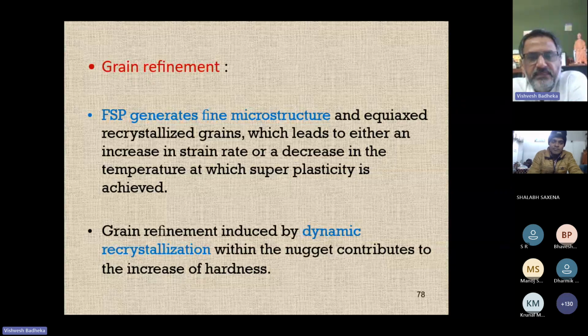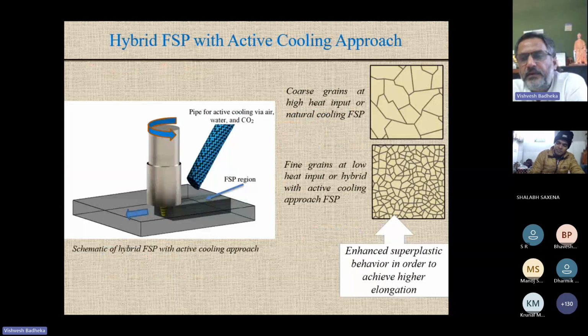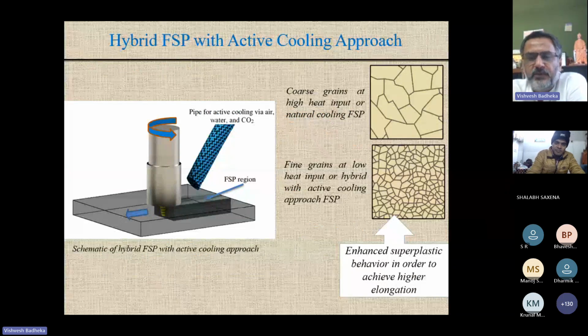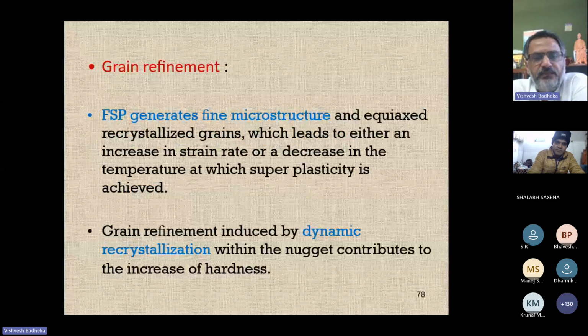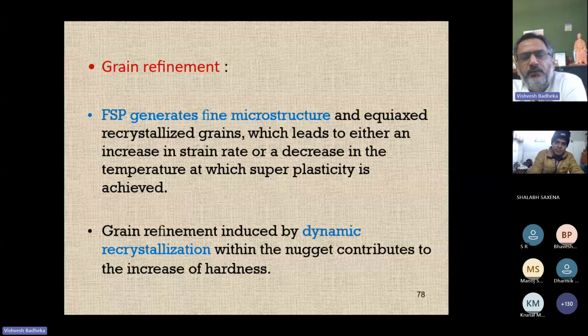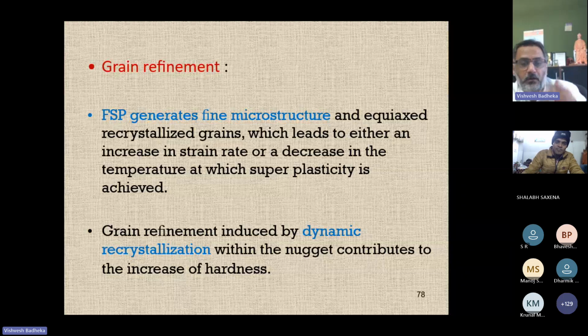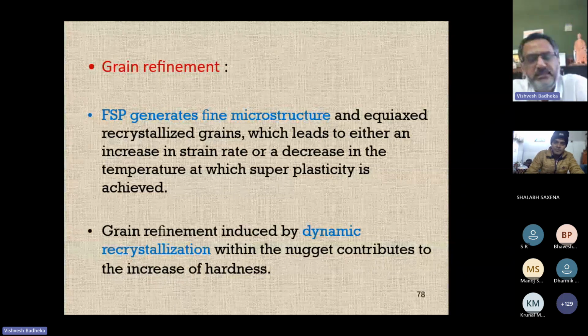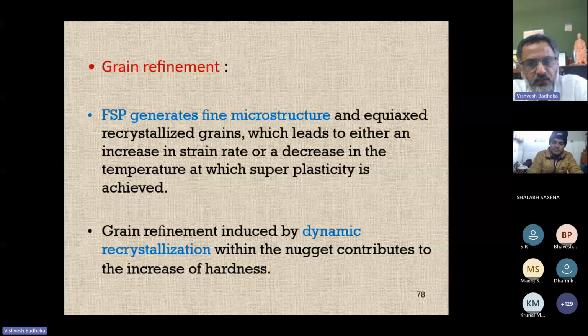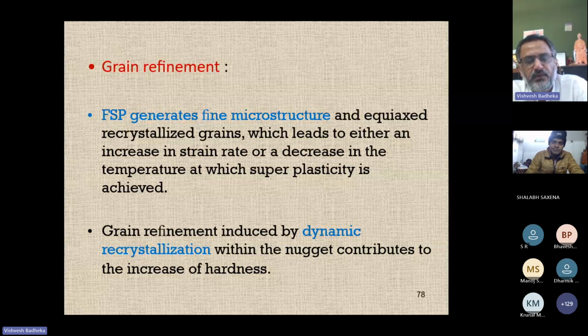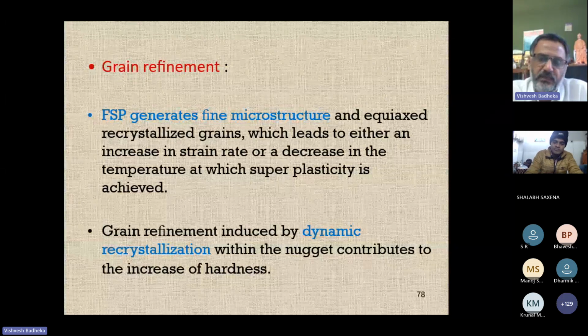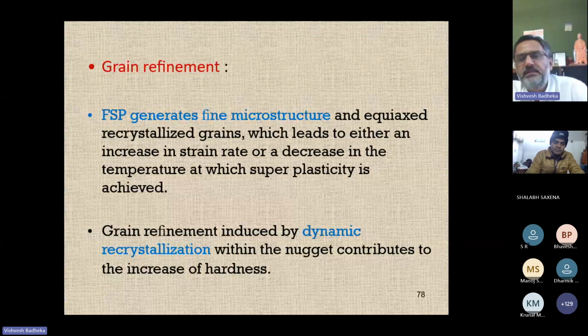Because of FSP, it generates the fine microstructure. Equiaxed recrystallized grain, right? You have seen in the earlier diagram the fine grain structure, right? And with the help of this FSP, this will help you to either increase the strain rate or decrease the temperature at which the superplasticity is achieved. Because industry is looking for high strain rate deformation because they have a production requirement. So the strain rate should be high, and the temperature at which you are achieving the superplasticity should be low. This is what the industry is looking for. Higher the strain rate and the lower the temperature.